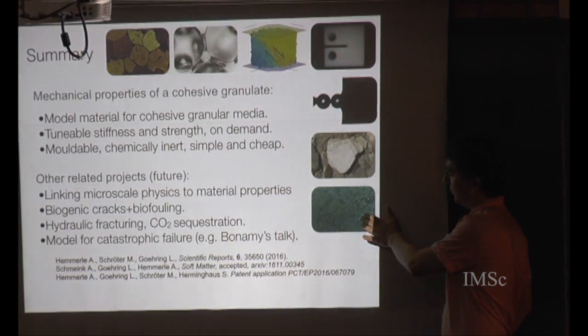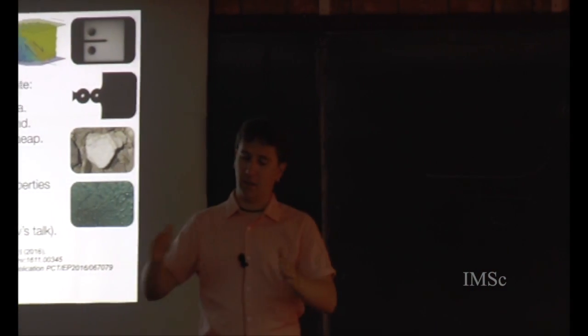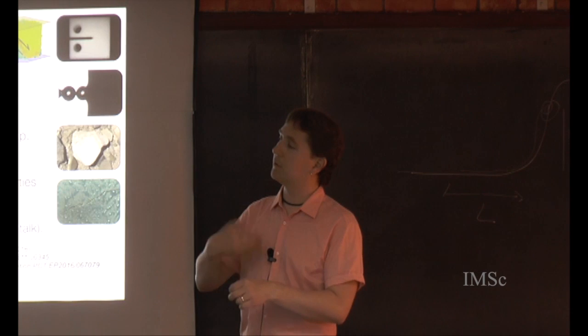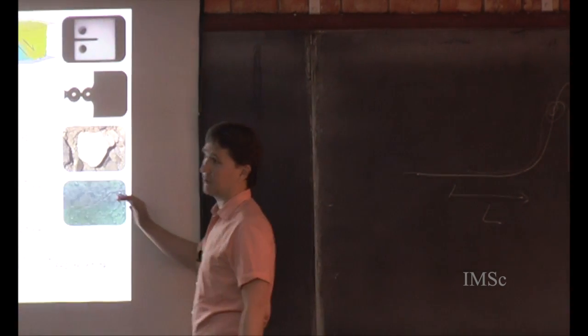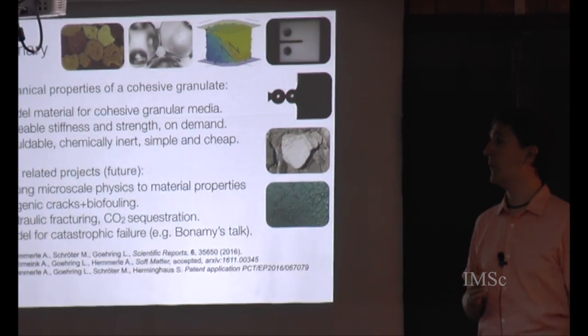But there's no obvious reason from fracture mechanics why that should be so. So the idea is we make a large cookie of this material, we put it in a Hele-Shaw cell with an injection point, we push water in under pressure, we add polymer, we do the same thing. We look under the conditions under which fracture happens. So that's the planned series of experiments with hydraulic fracture.